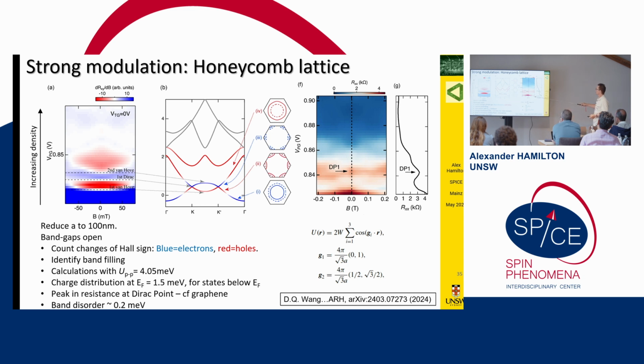This is a line cut at zero magnetic field, so this is sweeping the chemical potential. This is the resistance. As I come down and approach the Dirac point, there is a peak in the resistance that happens exactly when the chemical potential is there. So, I don't know. That peak occurs exactly where we predict the Dirac point to be. And we get a band disorder of about 0.2 millielectron volts compared to a band width of about 1 millielectron volt.